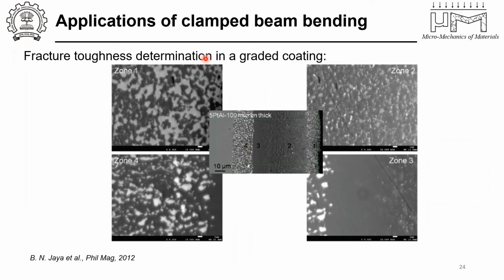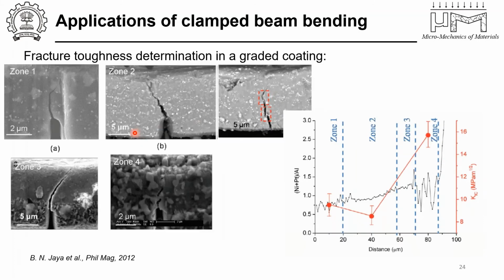Now, coming to some of the applications, what is shown here is a graded coating. This is a platinum nickel aluminide bond coat with a microstructure which is very heterogeneous across its cross section. So these are the different zones that we have identified. Not getting into the details of this, but you can see there are various types of crack growth mechanisms operating in individual zones, and the monotonic fracture toughness of each of these zones happens to be very different, and that you can measure only when you did micron scale testing like I was showing earlier.